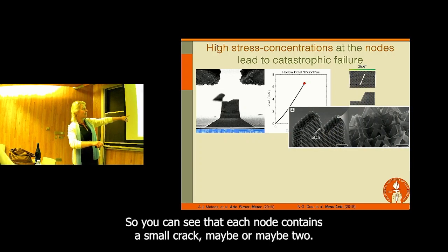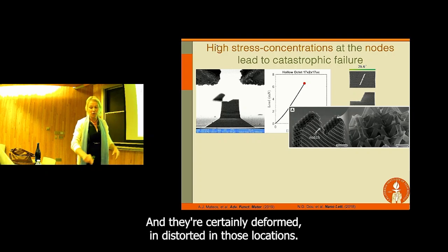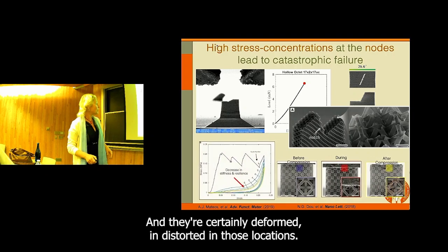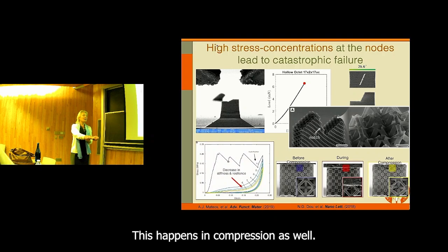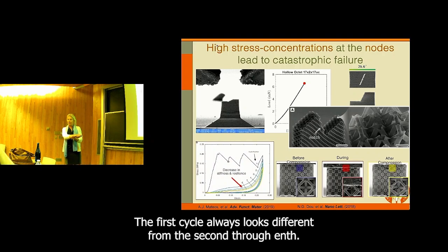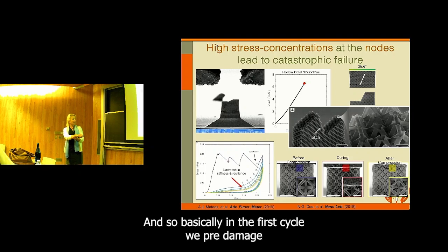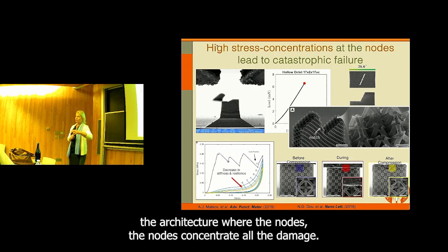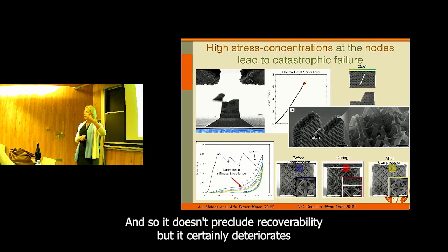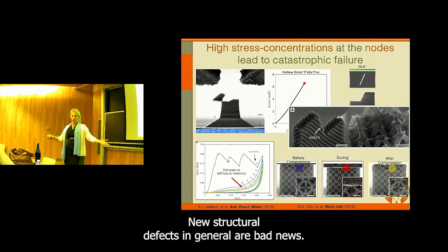So you can see that each node contains a small crack, maybe two. And they're certainly deformed and distorted in those locations. This happens in compression as well. The first cycle always looks different from the second through nth. Basically in the first cycle, we pre-damage the architecture where the nodes concentrate all the damage. It doesn't preclude recoverability, but it certainly deteriorates the strength. So nodes are bad news. Structural defects in general are bad news.